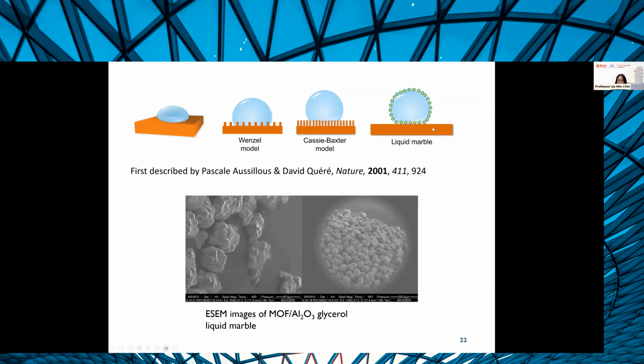And so it's like turning everything around on its head and looking at things from a different perspective. This means that you no longer have to functionalize your surface, you just functionalize your liquid to make it think that it's on a super oleophobic or super hydrophobic surface. And if you zoom in at the interface between the particles and the liquid, and one can do this via environmental SEM if you use a high boiling liquid for your liquid marble, you see that there are lots of gaps between these particles. In this case, these were the MOF particles I showed you earlier, and we had glycerol.